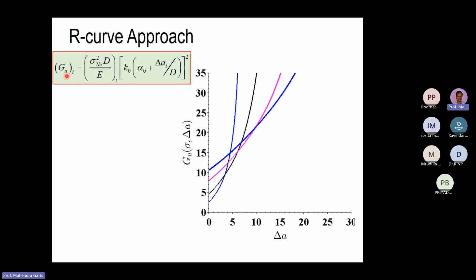If you plot these fracture energy curves as a function of crack length for a given size d, you get one curve, and as size increases, you get three more curves. So I plotted it for four sizes, d1, d2, d3, d4. This is the fracture energy curve as the crack length is increasing. Initially we have a crack length, and then as crack length increases, this is the fracture energy which is dissipated.